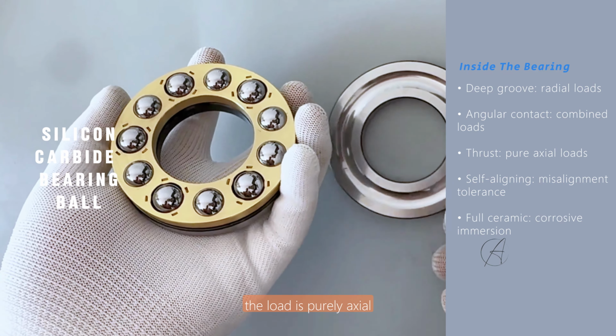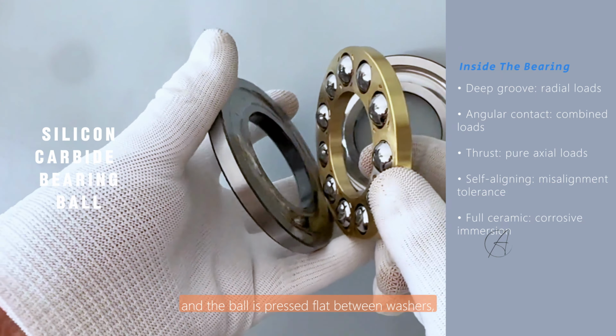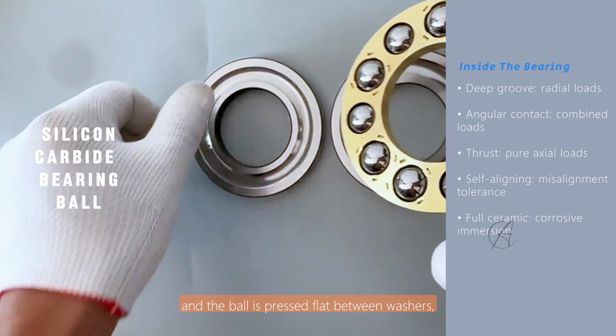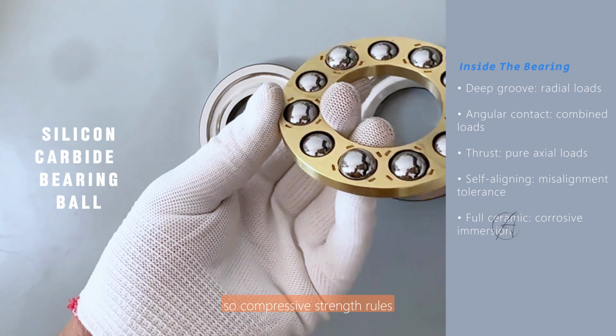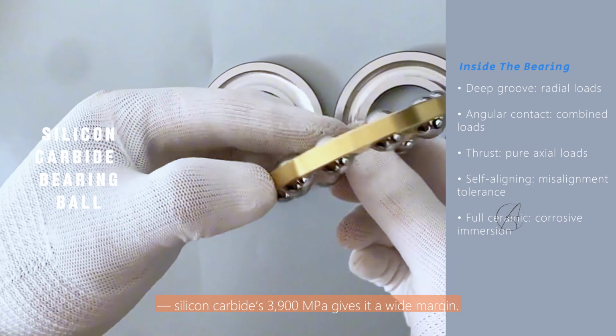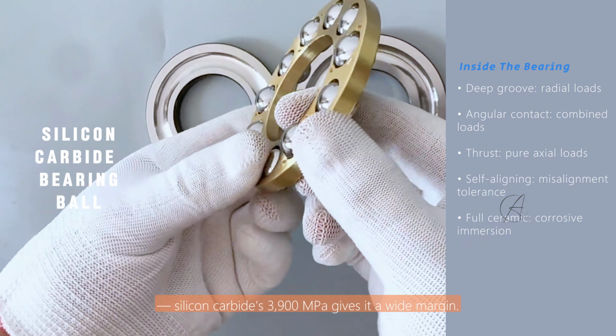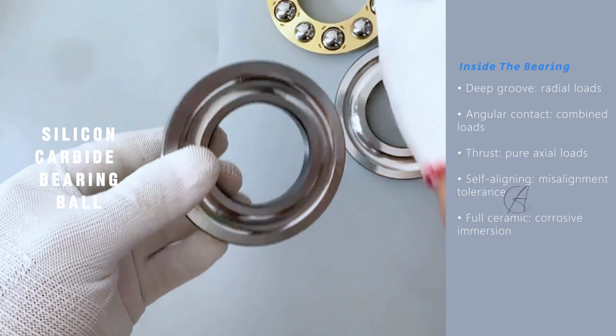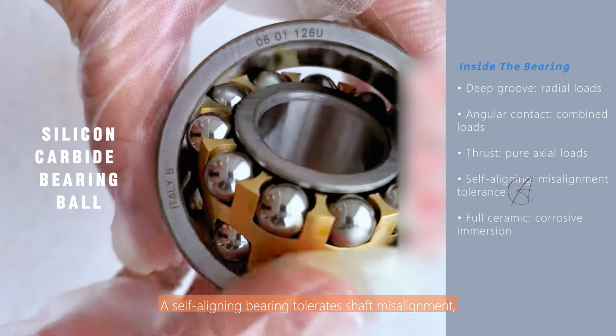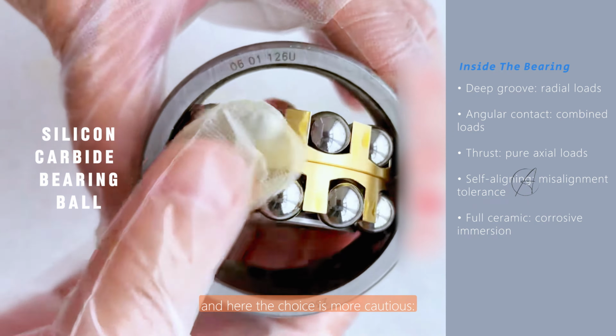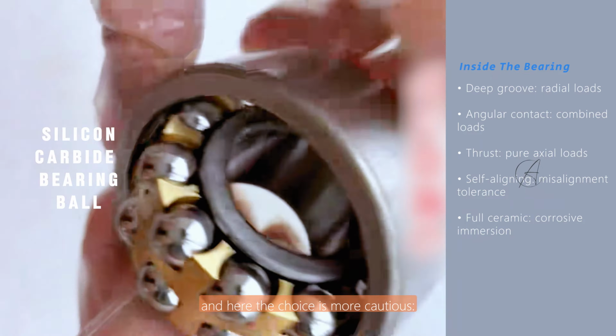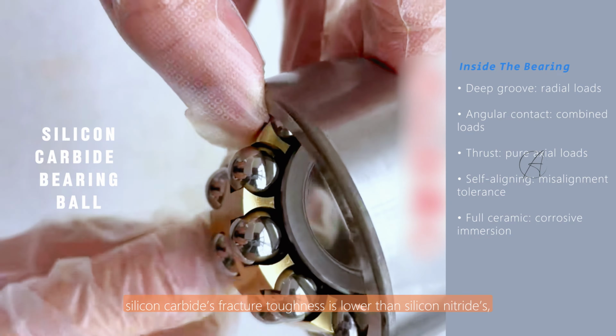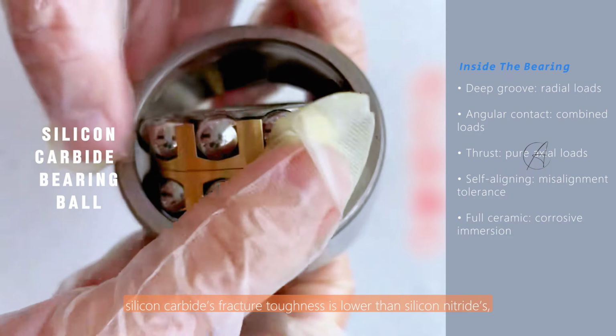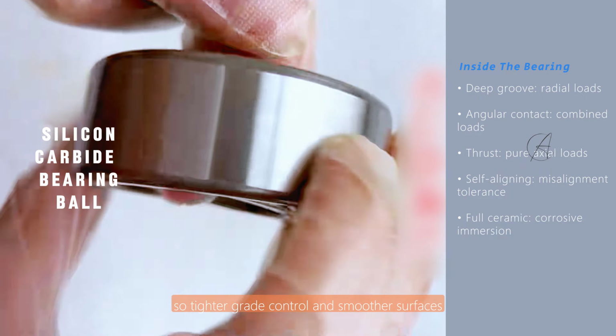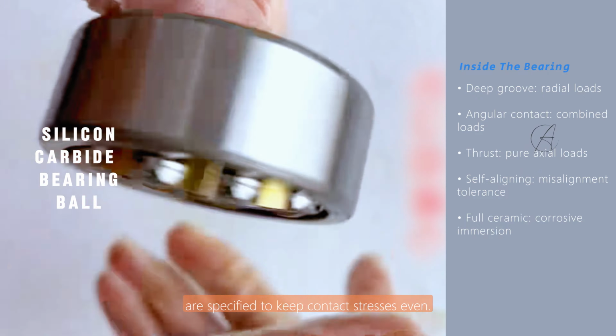In a thrust bearing, the load is purely axial and the ball is pressed flat between washers, so compressive strength rules. Silicon carbide's 3,900 megapascals gives it a wide margin. A self-aligning bearing tolerates shaft misalignment, and here the choice is more cautious. Silicon carbide's fracture toughness is lower than silicon nitride's, so tighter grade control and smoother surfaces are specified to keep